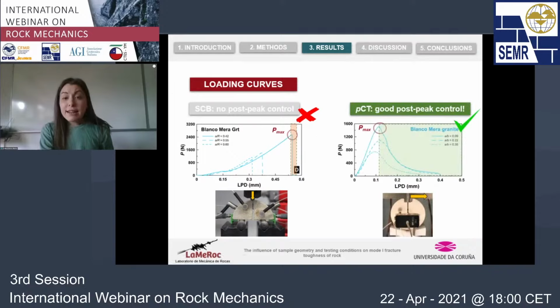On the other hand, if we take a look at the curves for the PCT, we also see that as this steel jaw here is moved, we observe that the load increases up to the peak. But then after this point, we have a very good control on the propagation of the fracture. And we have to further move the steel jaw to have further fracture propagation. So from this experiment, we can have much more information regarding the propagation of the fractures than in the case of the SCB.